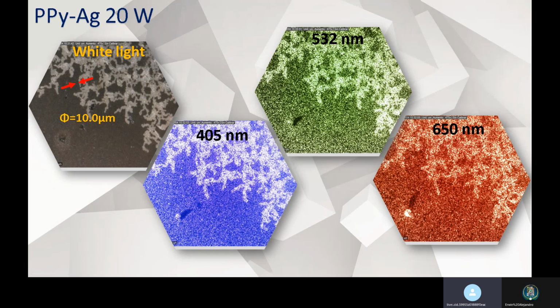Next, polypyrrole silver composite at 20 watts show a flat surface with tracks with 10 micrometers of diameters. Maybe silver continued to grow over the surface. Tracks are shine in all the light.